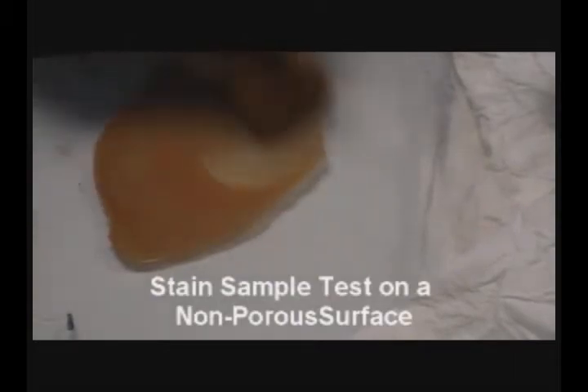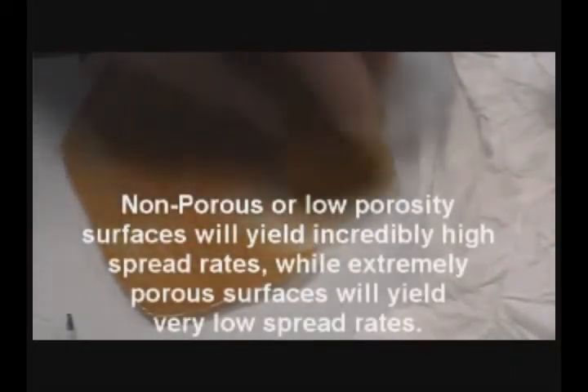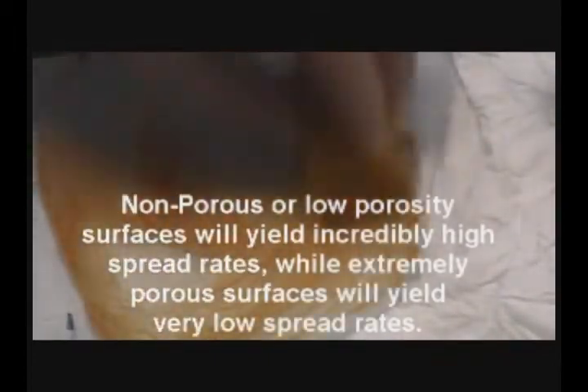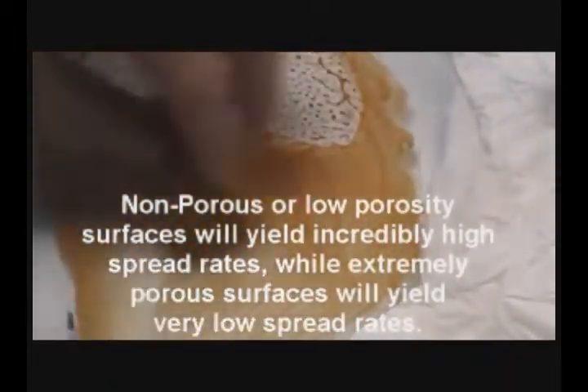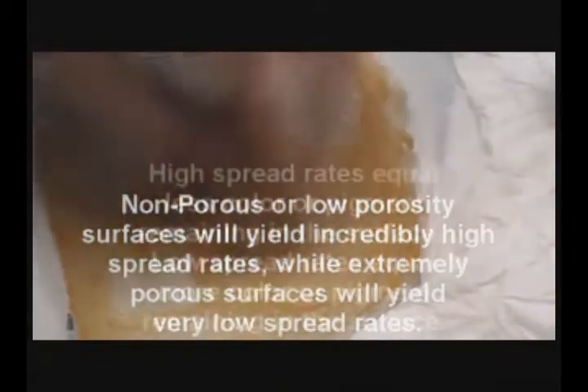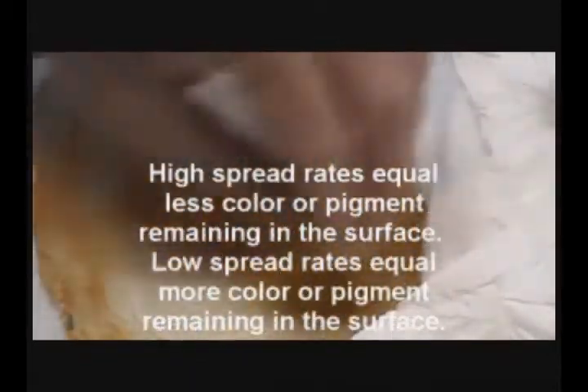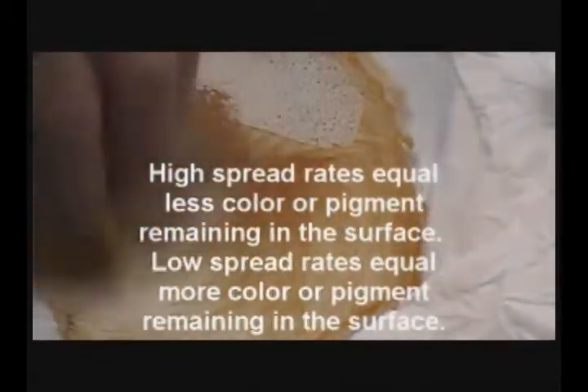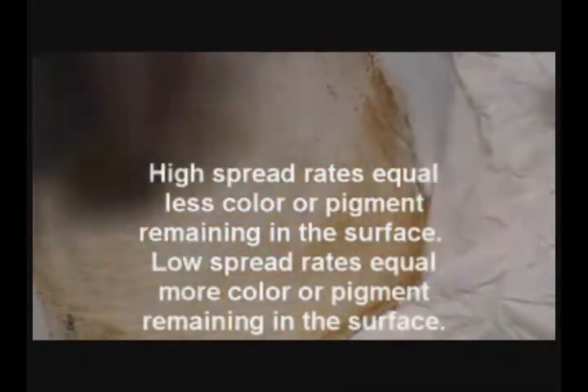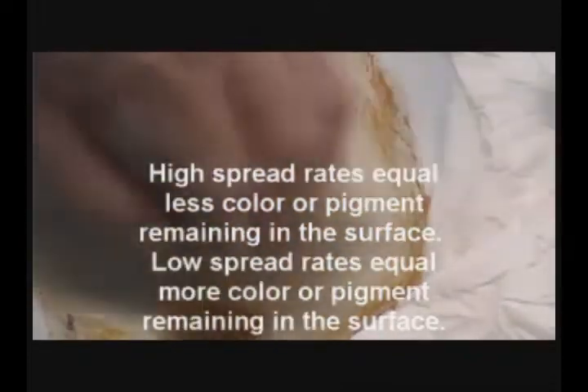Let's try a stain sample test on a non-porous surface. Non-porous or low porosity surfaces will yield incredibly high spread rates, while extremely porous surfaces will yield very low spread rates. High spread rates equal less color or pigment remaining in the surface, while low spread rates equal more color or pigment remaining in the surface.